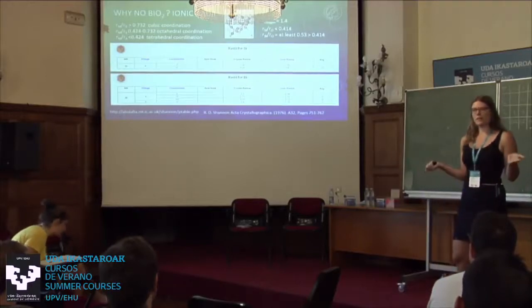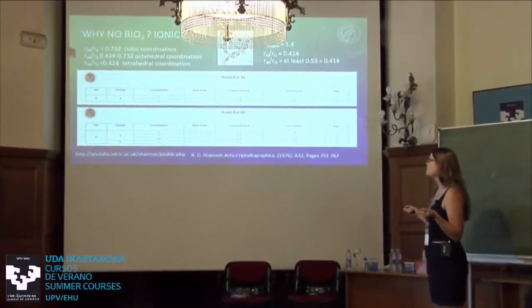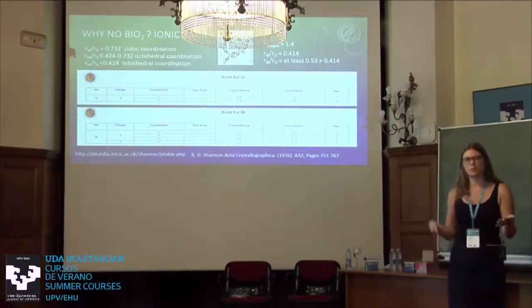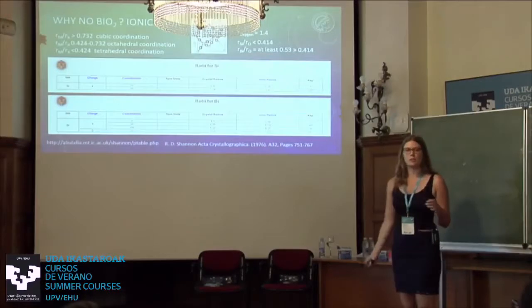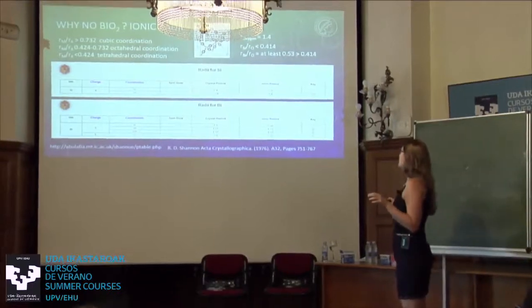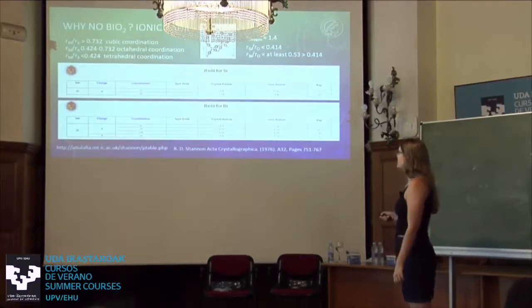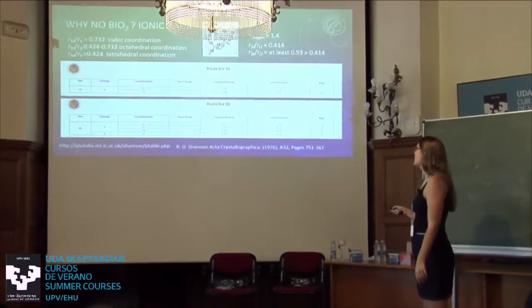Okay, why does this not work? So one is, I mentioned in the beginning that the ionic radii are important to form a crystal structure. And so if you look at the rules again, I listed them again here, you take the ratio of the metal, so in our case silicon versus oxygen or bismuth versus oxygen, and you get the coordination. And so you can look up the radii, and under this link I put here, the Shannon crystallographic radii, they're all listed on the internet, and you can just go to this page and look at radii of materials. So the radius of oxygen is 1.4. If you look up the radius of silicon, it is 4 plus in this compound because in SiO2, oxygen is 2 minus, so 2 of them, silicon 4 plus. If you look up the radius of silicon with charge 4 and tetrahedral coordination, because you see here there is a silicon and there are 4 oxygens around it in the structure they draw, then we find an ionic radius of 0.2.